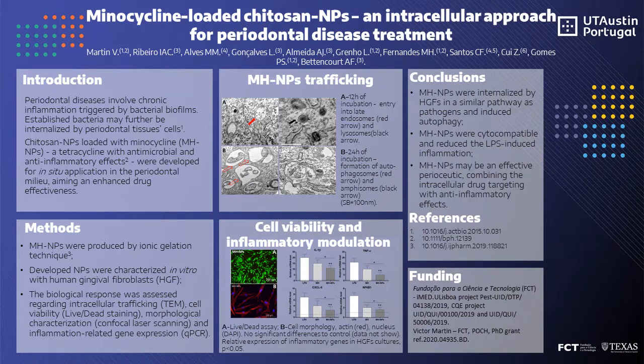Finally, to analyze inflammatory modulation, we stimulated cells with LPS for 24 hours prior to nanoparticles incubation. Cells were also incubated with minocycline solution. Control is represented by the line at one value. As we can see, nanoparticles downregulated the expression of these four inflammatory genes more efficiently than the minocycline solution.